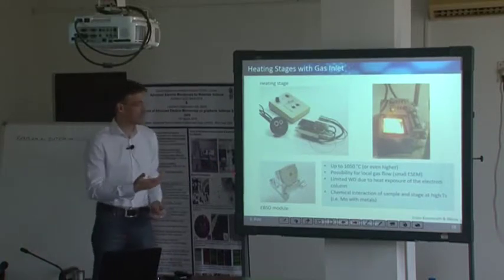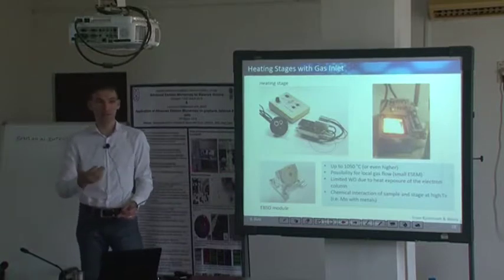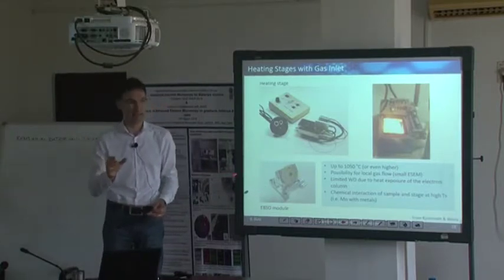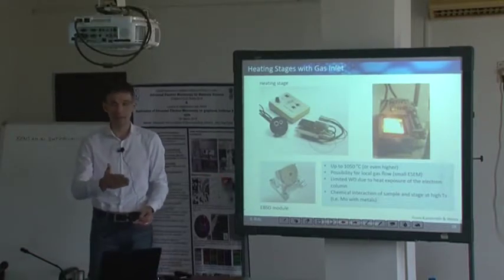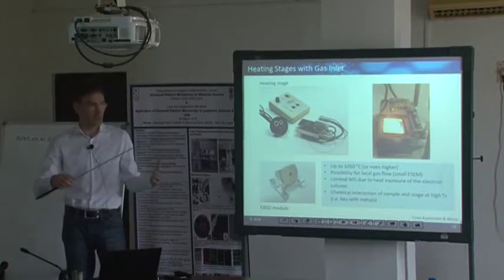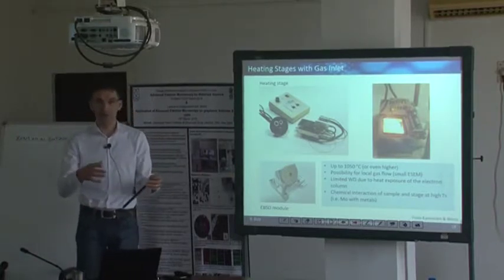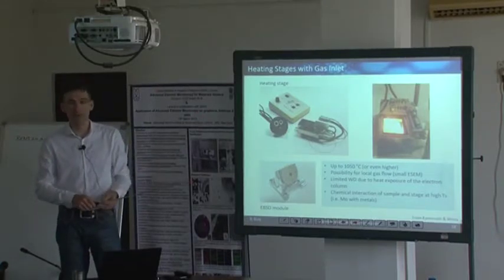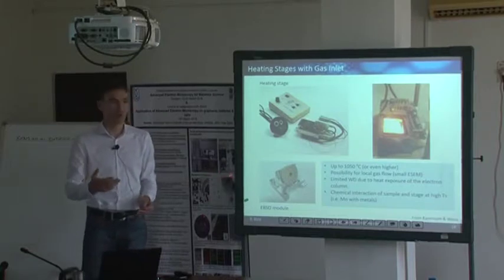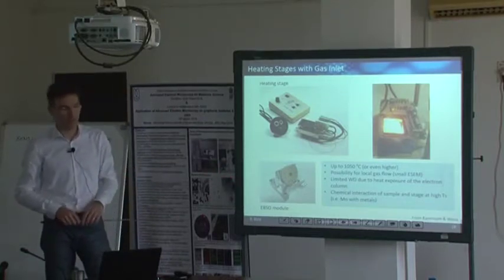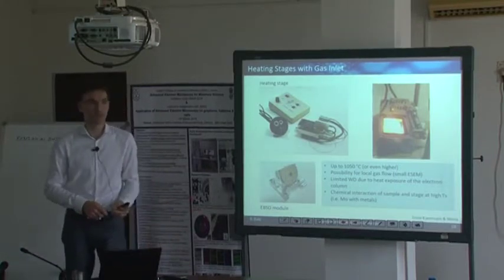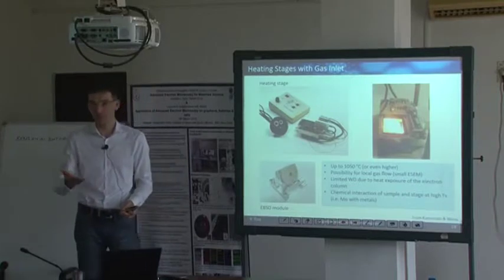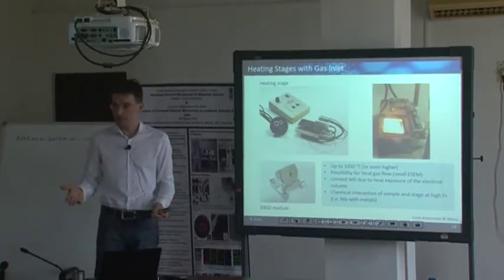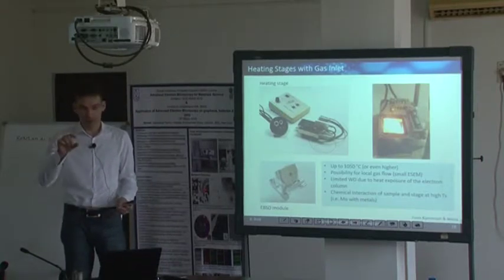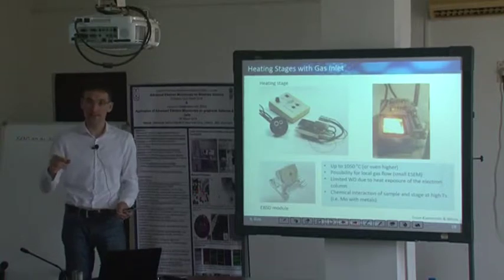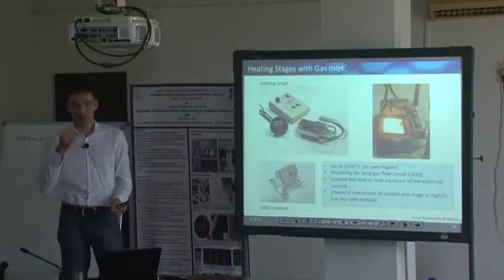So in principle, for such experiments, you would need, but this is very challenging, certain ways to measure the temperature on a very localized scale, either by, let's say, electron diffraction, because heat causes thermal expansion, which causes a shift of your lattice planes or a change of your lattice parameter, and by that you are able to observe changes of your diffraction pattern and your spacings. But you have to be very accurate to achieve that. The thermal expansion coefficients of common crystalline materials are of the order of 10 to the minus 6 to 10 to the minus 5, and observing any temperature change of a few Kelvin necessitates such an accuracy in electron diffraction. And we just published on that one year ago.